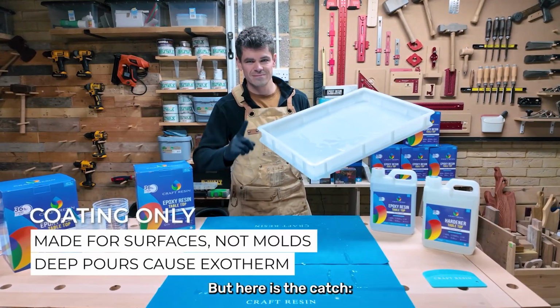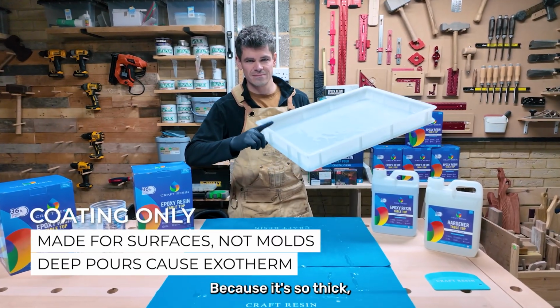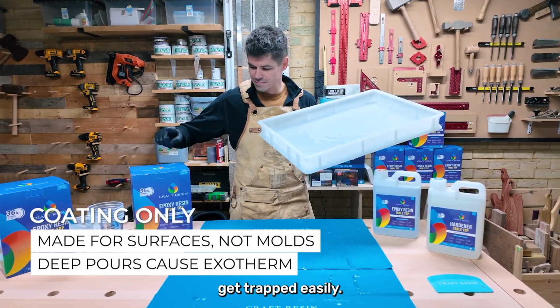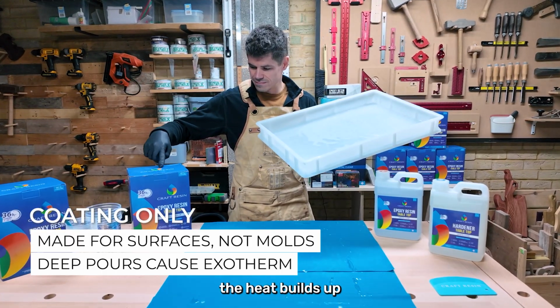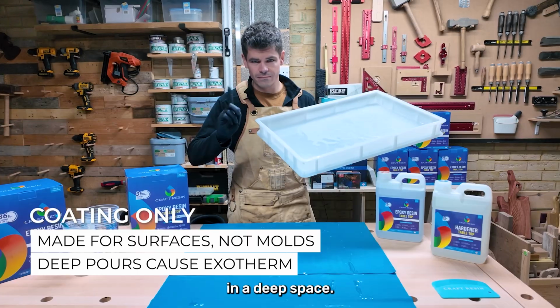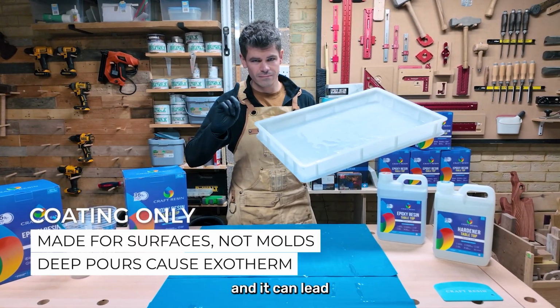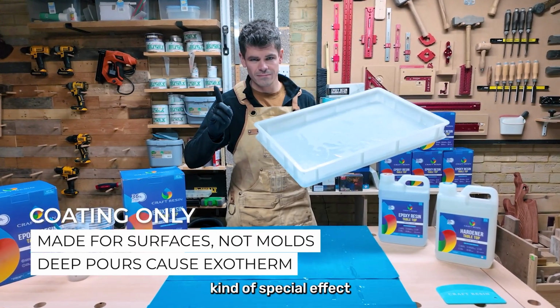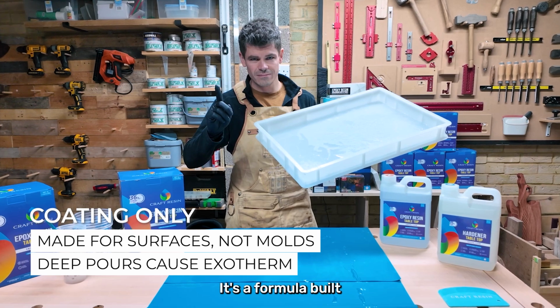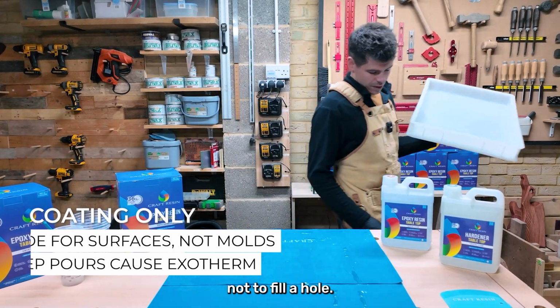But here is the catch: never use this for moulds. Because it's so thick, air bubbles get trapped easily. Even worse, the heat builds up way too fast in a deep space. We call this exotherm, and it can lead to smoking or cracking, and that's not the kind of special effect we want. It's a formula built to coat a surface, not to fill a hole.